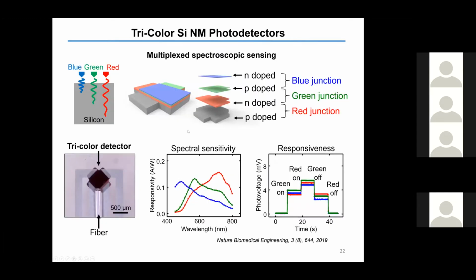In the next example, we replace the silicon nanomembrane photodetector with a tricolor silicon photodetector. Therefore, we only need a low-cost white light as an external light source to enable simple spectroscopic sensing simultaneously and continuously. The idea is based on the wavelength-dependent penetration depth inside silicon, where red light with a long wavelength can penetrate deeper, and blue light with a shorter wavelength can only penetrate shallow depths inside the silicon. So if we dope the silicon layer by layer to form a vertical stack of alternating NP-NP doped regions, we can obtain 3 photojunctions at those interfaces.